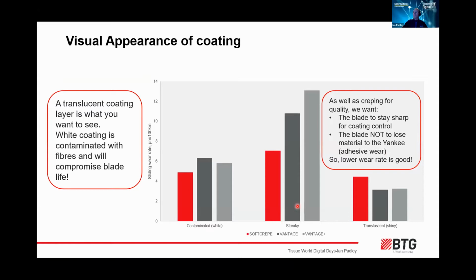Now, all the charts are going to be the same. On the vertical axis here, we're going to show the sliding wear. And what we're looking for are the lower values. And on the bottom, we've got the categories. In many of these, I've got three very common types of BTG high performance creping blades. And we see here that the translucent looking coating gives the low wear. That's what we're looking for. With this type of low wear, the blade is staying sharp, getting good coating control, and we're not losing material to the Yankee. We're not getting adhesive wear. So the lower wear rate is good.